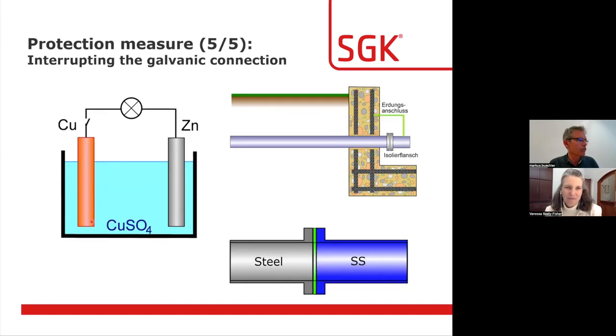And now what is the good solution to this is, if you want to save the lifetime of the battery of your flashlight, you switch it off. And that's the correct way of mitigating galvanic corrosion, which means that you still keep your earth equipotential bonding, but you introduce an insulation flange here. And that's going to eliminate the corrosion issue. So that's what we try to do whenever possible, as a straightforward and reasonably cost-effective means of eliminating galvanic corrosion issues.